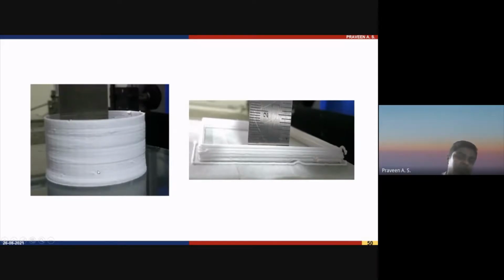Finally we arrived at a composition of 55%. With this pneumatic type of extrusion system, we can handle this slurry of 55%. But now we are trying to develop a screw extrusion in order to handle higher viscosity values, because as I told you, whenever you increase the solid loading, your part strength also increases. Obviously this is alumina, so I have to sinter this sample at a higher temperature, around 2000, for a different thermal cycle. That may cause some shrinkage or cracking of the structure. That is another challenge we have to face.